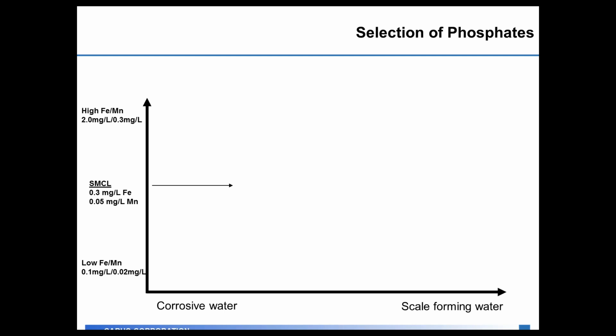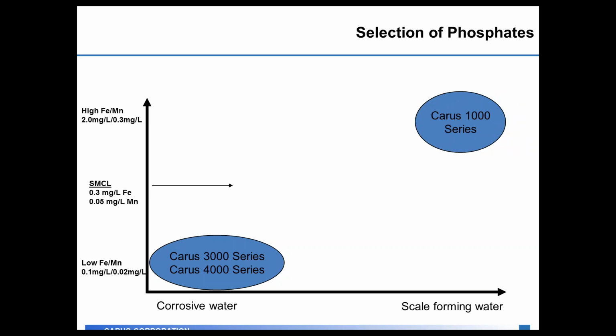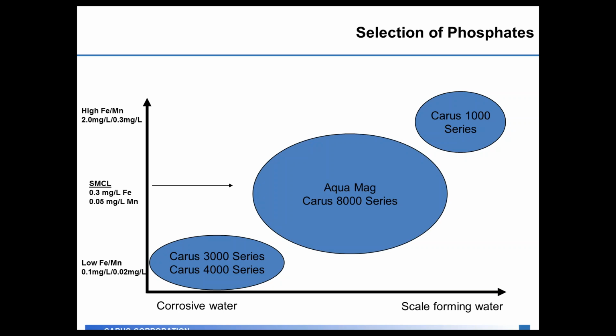In general terms, kind of give you an idea of where you would start with a phosphate product. If you have no iron and manganese, and you have a corrosive water which has a low hardness, low alkalinity, then you would be in the product line of orthophosphates, which would be the Carus 3000 or Carus 4000 series. If you have a lot of iron and manganese, so say 2 milligrams per liter of iron or 0.3 milligrams per liter of manganese, or you have a very high hardness, 200, 300, 400 milligrams per liter, then you'd be in a product that's straight polyphosphate, the Carus 1000 series. For most water qualities, you'll fall in the middle between those two ends of the spectrum, and you'll use a blended phosphate, which would be the Aquamag or the Carus 8000 series. And the blend ratio will change to more polyphosphate the more stuff you have to sequester in your water. Whereas if you're more focused on lead and copper control, you'll have a higher orthophosphate versus polyphosphate ratio.